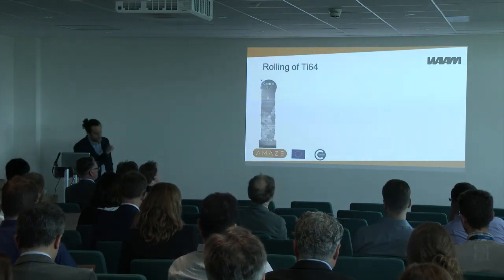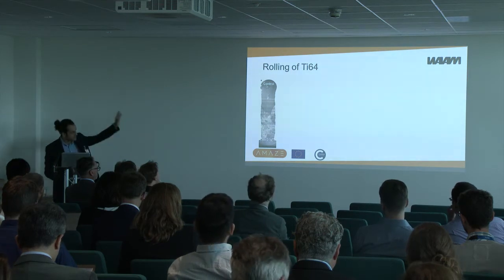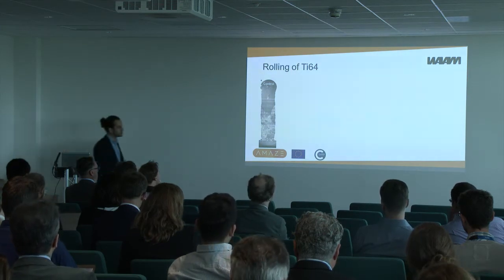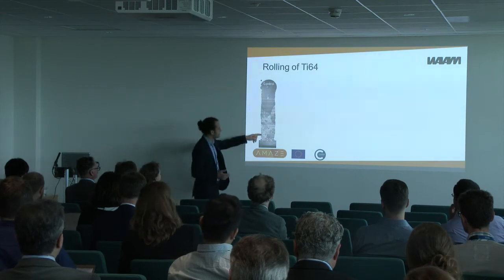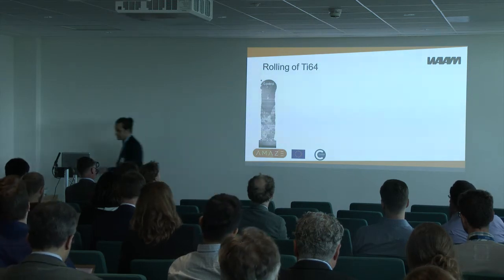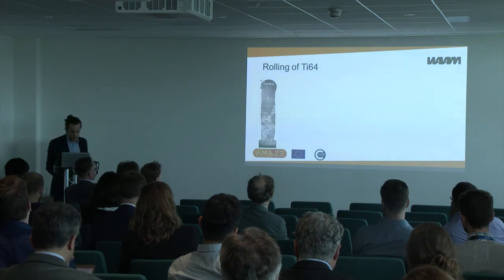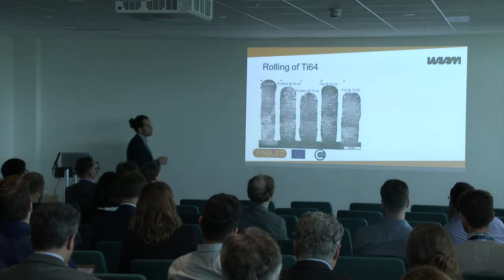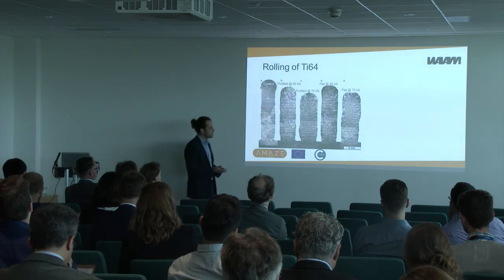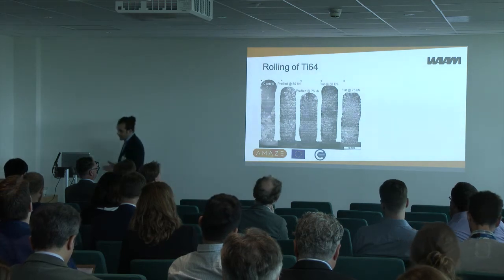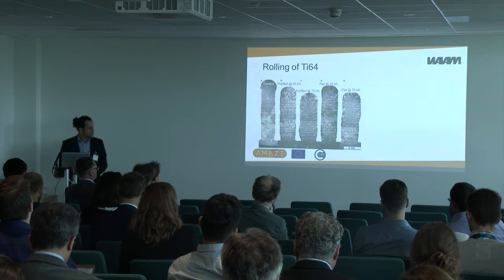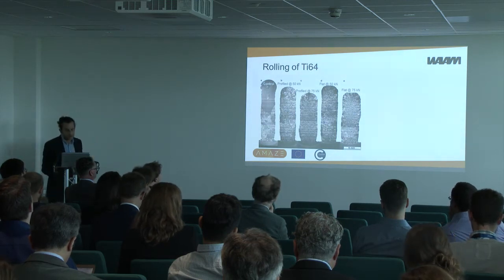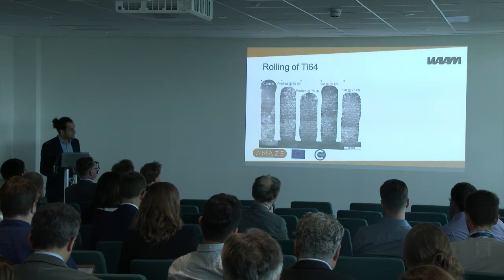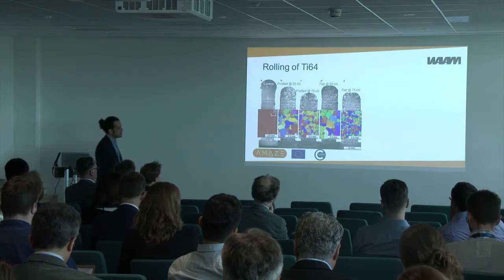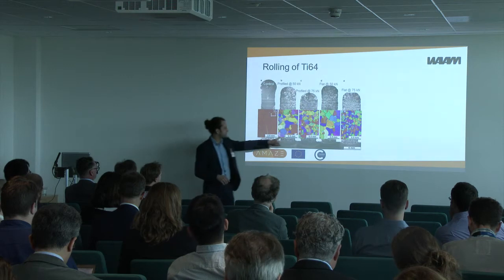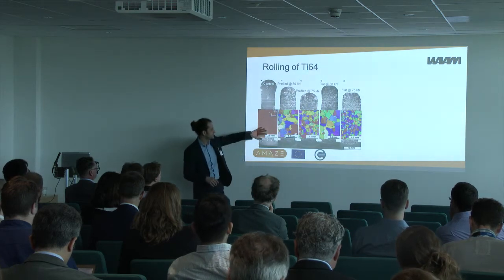So again, recapping the control specimens with the big grains, if you do in-process cold work, which means doing a rolling pass every time you do a layer for the time being, the microstructure changes substantially. We go from a columnar configuration to grains that are much smaller, and they are equiaxed. We have produced grains, in this case, I think as small as 70 micron in diameter. Then we also looked at the texture, and we saw that the texture is changed. You can see, first of all, the completely different scale bar. So these grains are actually much smaller than what you can see there.